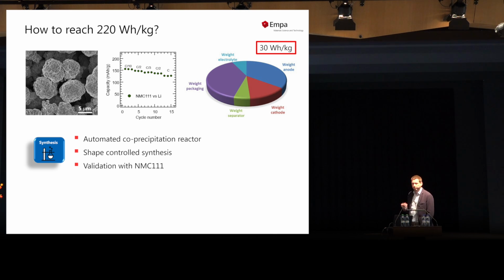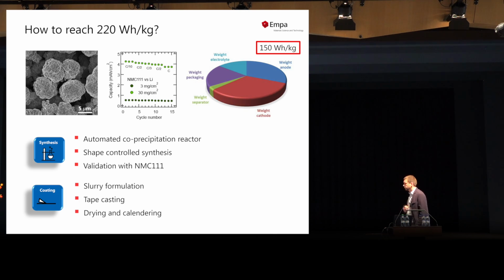So in order to improve the energy density here, we had to put quite some effort into the coating process, on the level of slurry formulation, tape casting, drying, calendering. This is not a scientifically very rewarding task. It's a lot of trial and error, but we have to go that way to get to better cells.